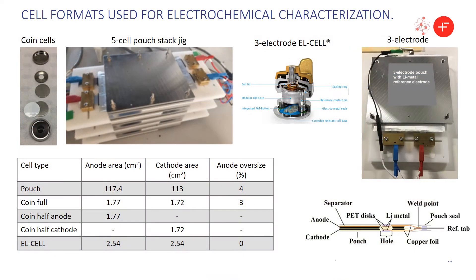After understanding the tables, we designed four types of cells. This figure shows the configuration for the coin cell, and this one shows the pouch cell jig. The pouch cells are compressed between two brass blocks to decrease the contact resistance. This figure shows the three-electrode coin cells, and this one is for the three-electrode pouch cells. This table shows the electrode area for the electrodes.